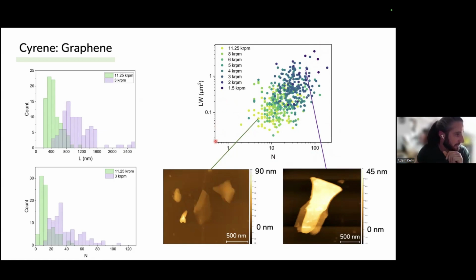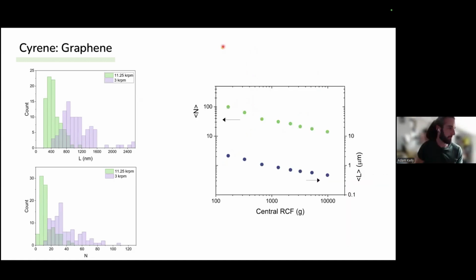Now, one other thing to note in here is that even up at speeds of 11.25 kRPM, we find no monolayers. We find perhaps one bilayer, maybe two trilayers. So we're not producing any monolayers, bilayers, or few layers, but it may be the case that they're in the dispersion, but these centrifugation speeds simply can't get them out. So plotting the distribution of layer number, distribution of length against the g-force that we're centrifuging at, we find an inverse relationship, which is proportional to 1 over the square root of g.